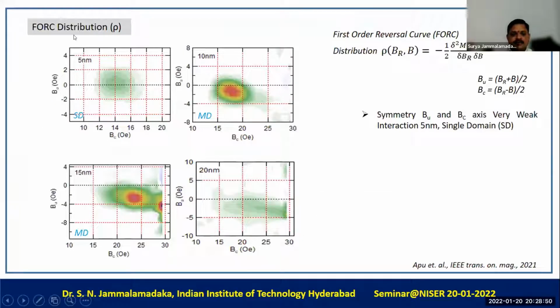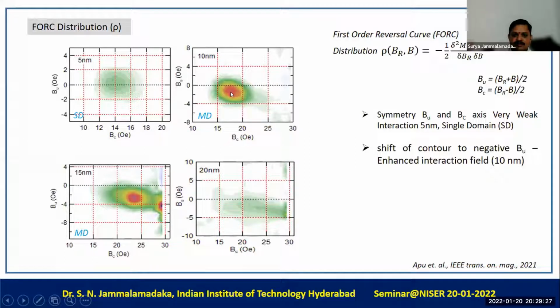We also plotted the FORC distribution, the contour graphs. From the contour graph, using this distribution function, on the x-axis we have BC and on the y-axis it is BU. The contour diagram is symmetric for the 5 nanometer film. Whenever you have a symmetric contour diagram, you can say that you have a single domain. However, as the thickness of the film increases to 10 nanometers, we see a shift of this contour diagram to the negative side, which demonstrates that the magnetostatic interactions are increasing a little bit.